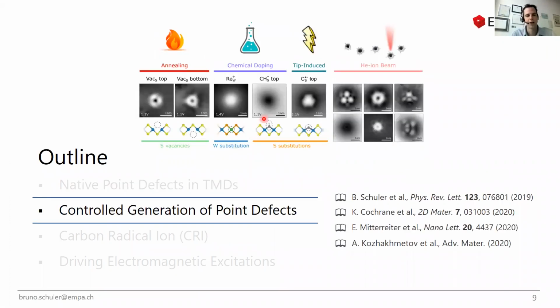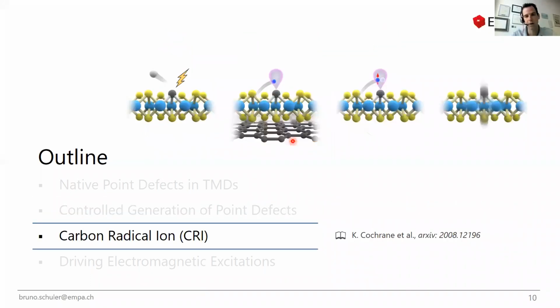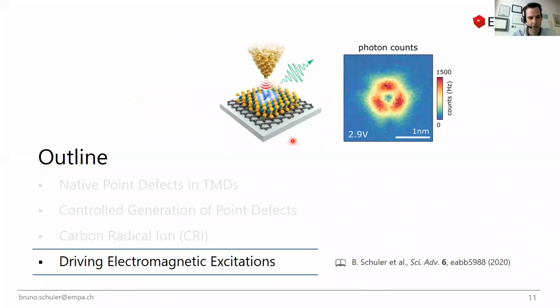And then we look at how we can controllably introduce those defects by different means, for instance, by some thermal annealing, by chemical doping, through atomic manipulation, but also through some lithographic means. Then we pick one example, which shows some very interesting states. That's something we call the carbon radical ion, which we just recently put on arXiv. And then one instance where we could drive electromagnetic excitations at individual point defects in these TMDs.